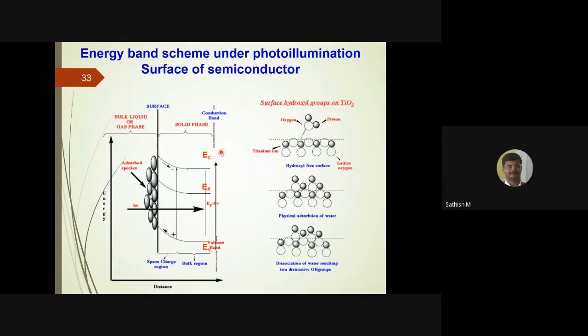Here, as I told you, in the photocatalytic system, TiO2 is well known. It is also commercially used, though the activity is very poor, as it can absorb only the UV light. People are still using this for various reasons. One is that it is a very stable system, and it can easily oxidize. So generally it is used for the oxidation reaction, that is the removal of pollutant or dye molecules. For any oxidation reaction, TiO2 is very strong.